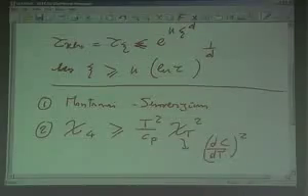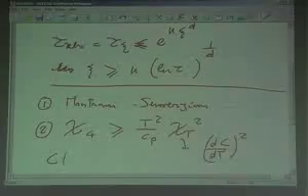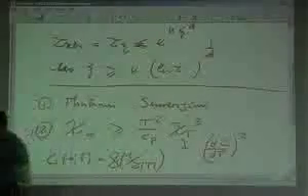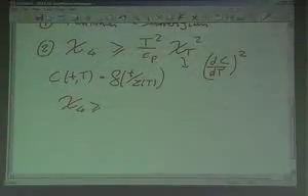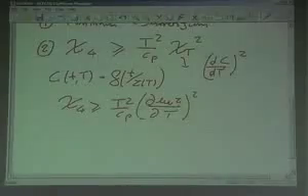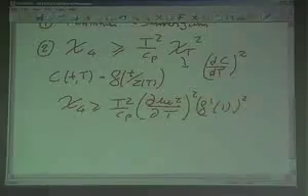If you take, let's say, for the correlation function as a function of time and temperature, a scaling relation, just to be simple, f of t over tau of the temperature, and you plug it into this inequality, you get that chi4 should be larger or equal than T squared divided by C_p, times the derivative of log of tau with respect to the temperature squared, and there is a constant here, which I think is f prime of 1 squared. Don't care about the constant.